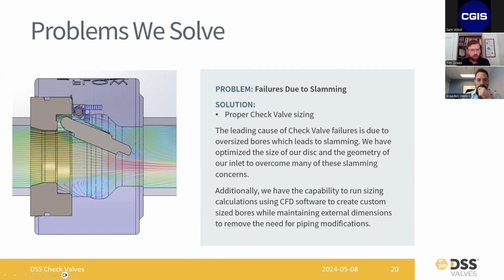Another problem, probably one of the more common reasons that check valves fail across all industries, is slamming due to improper sizing. Check valves are not typically thought of as the smartest product out there, and not a lot of thought goes into sizing. Typically, people put in a check valve based on the line size. If they have an 8-inch line, they put in an 8-inch bore. A lot of times, because the disc requires a certain amount of velocity to stay fully open and stable, there's not enough velocity to keep it open, and you see slamming.